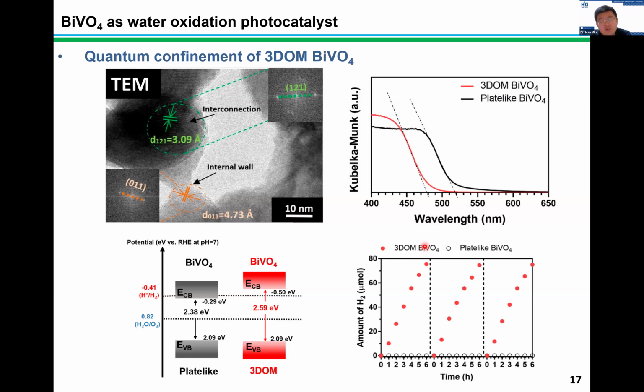So this is the first time for us to report that the 3DOM structure of bismuth vanadate can induce quantum confinement effects, which shift it from a water oxidation catalyst into a hydrogen evolution catalyst, which is very meaningful for the following studies to design the one-step excitation for bismuth vanadate for overall water splitting.